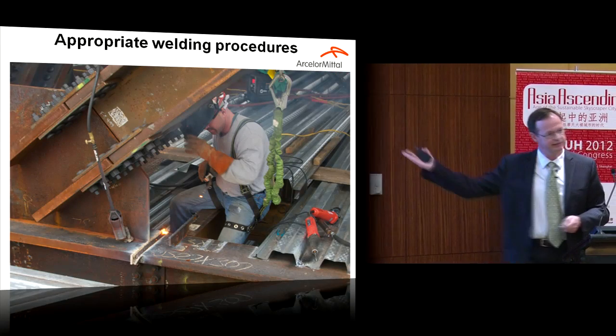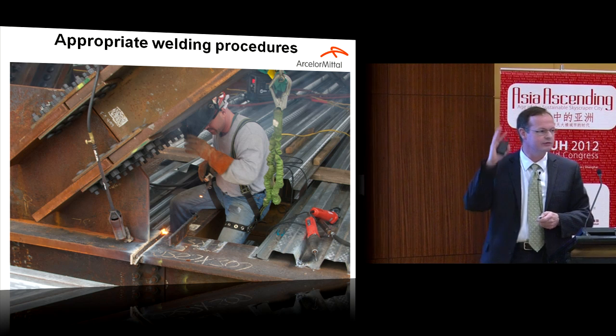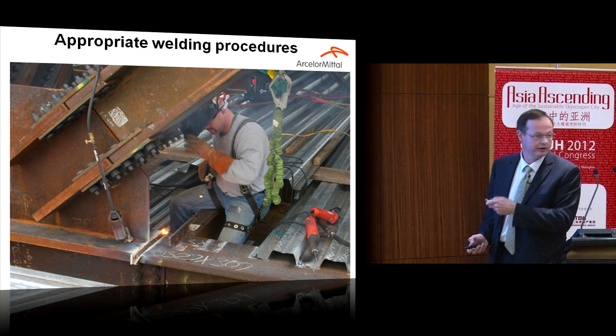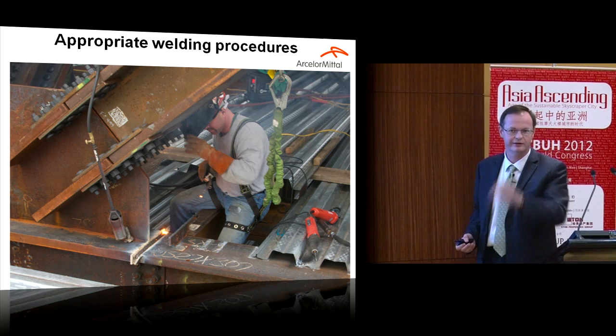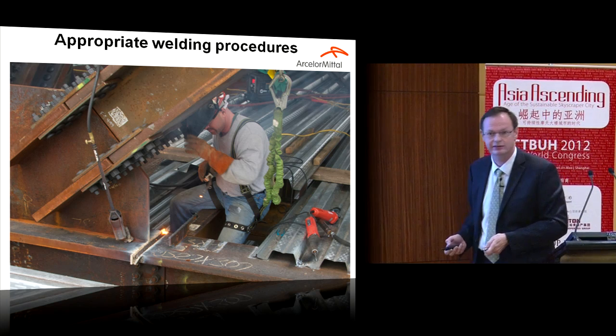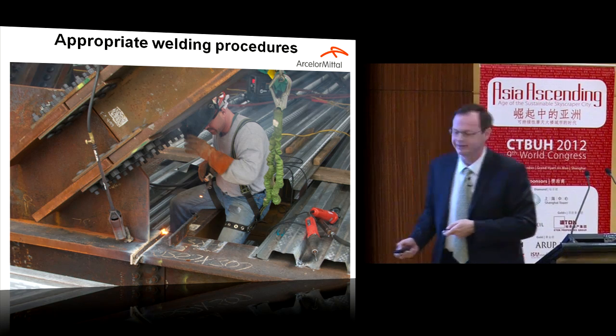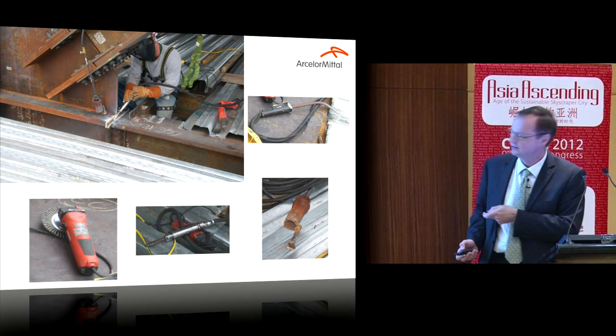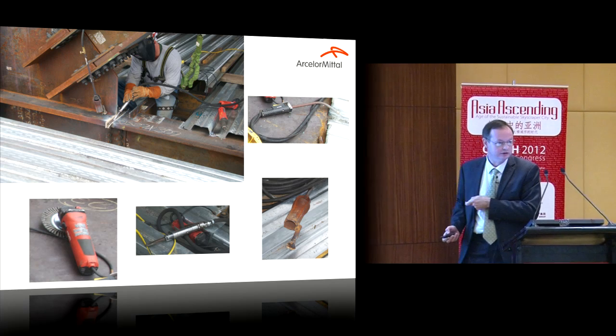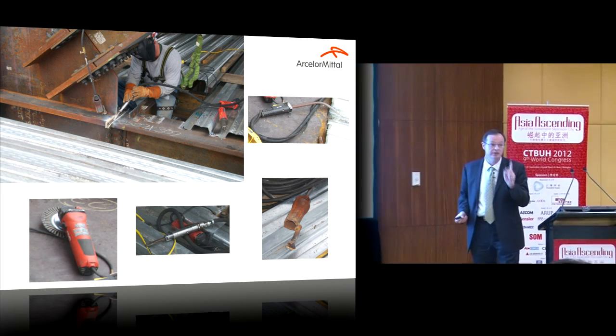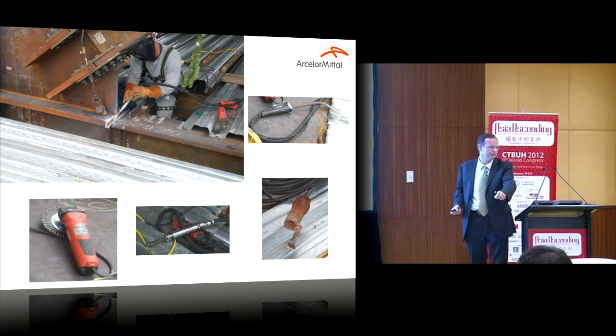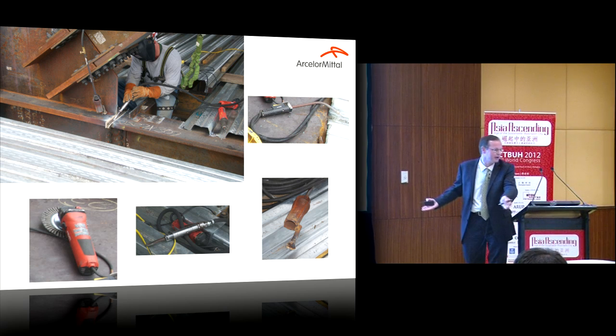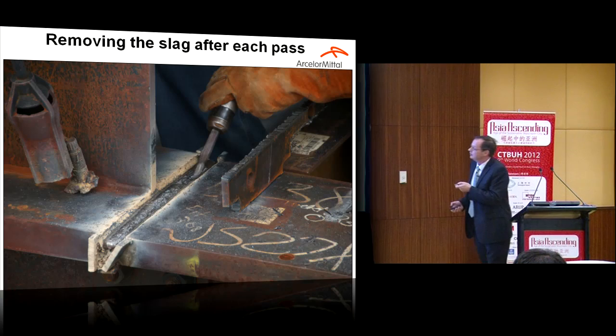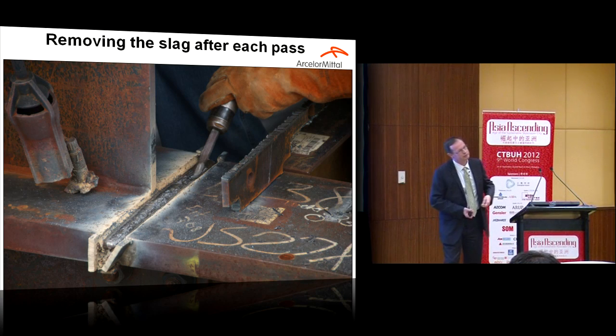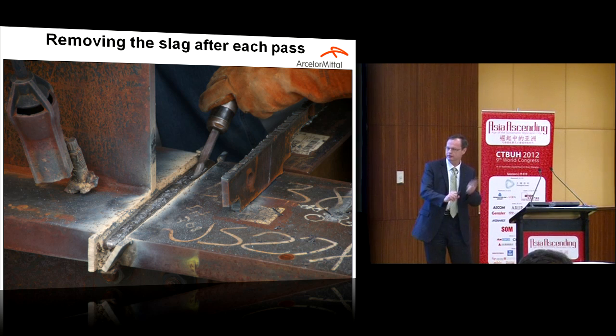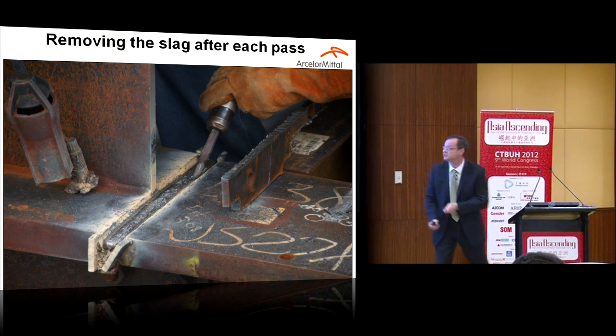If you go to the States, these are slides from New York, from a new high-rise in the States. When you see a welder, and we will see tomorrow, I don't know if you are going to see the job site of the Shanghai Center, you see they have tools all around. You see a grinding machine, you see a hammer, and you have the torch, because even if the steel doesn't need to be preheated, you must remove the moisture if you follow the codes, the D1.1 codes, for example, AWS. And after each pass, normally, you have to remove the slag. So you need a hammer and remove the slag.